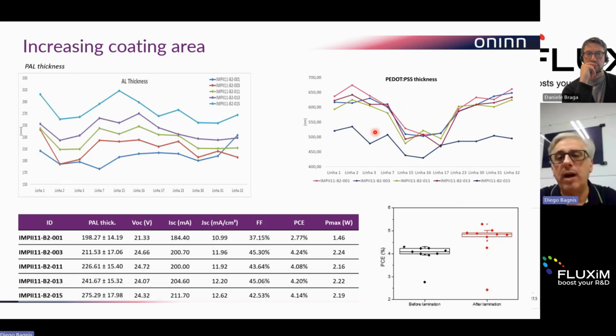But in the end, when you arrive at a realistic production, you have to take much more parameters into consideration, and so you maybe have to find the right compromise in order to get a realistic product. This does not mean that you have the best or highest performance possible. On the other side, it is pretty interesting as well that before lamination, the performance is much lower than in the R&D. This is still not the last results, but just to show the concept.